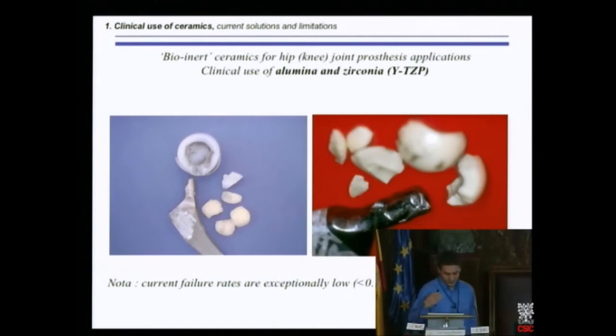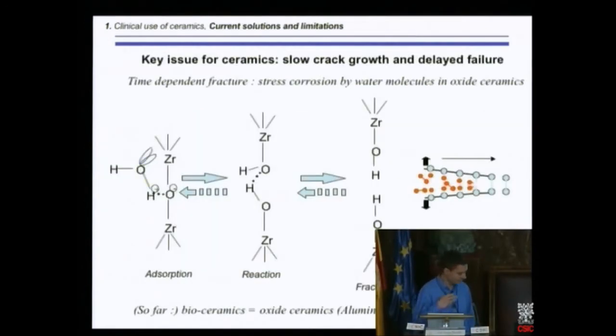We can have some failures. The failure rate is very low, less than 0.1%. We said for Biolox alumina, for example, 0.02%, so that's quite low. But we are limited in terms of designs with alumina. So we have designs which are limited in the case of alumina. We have also talked about slow crack growth.